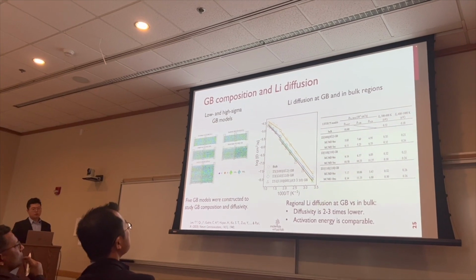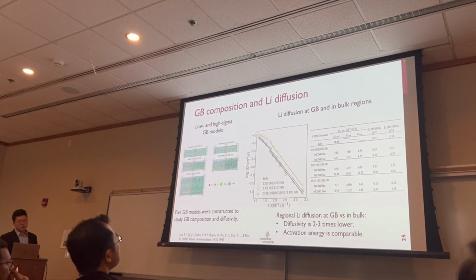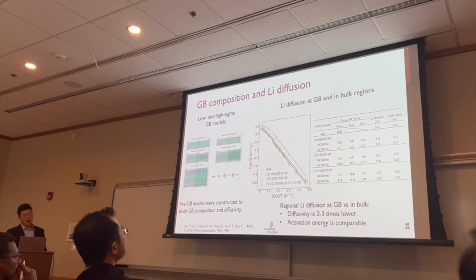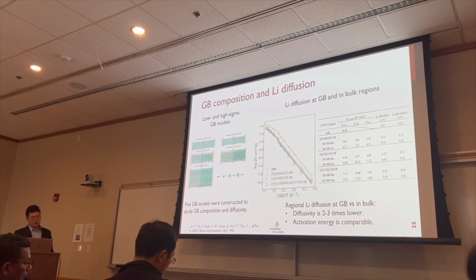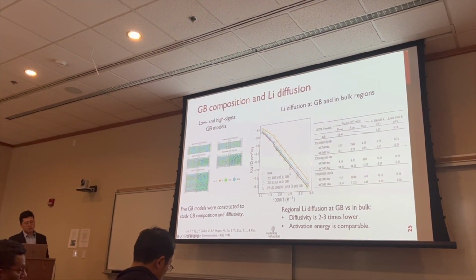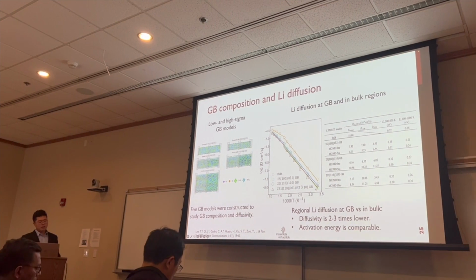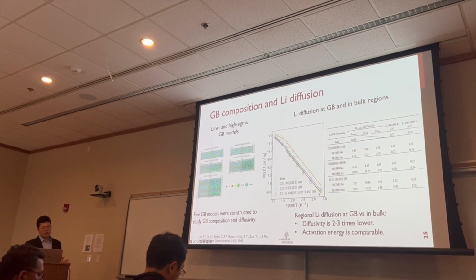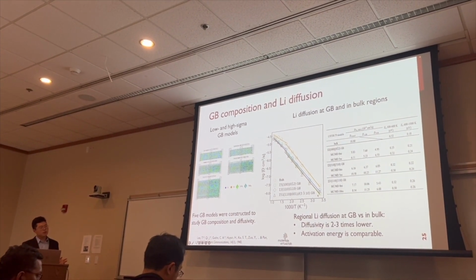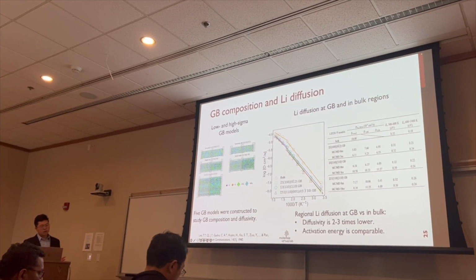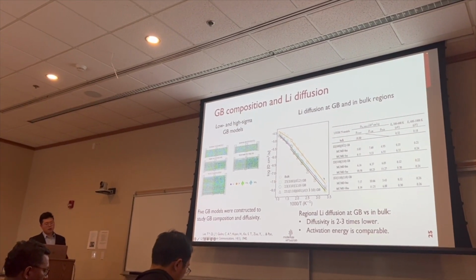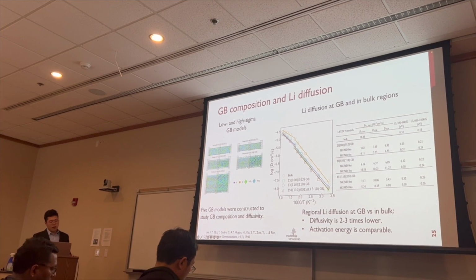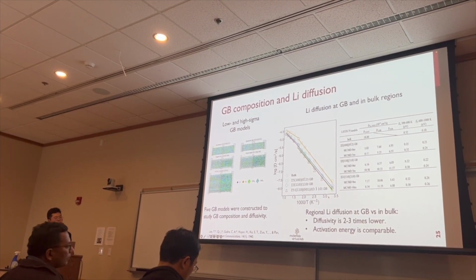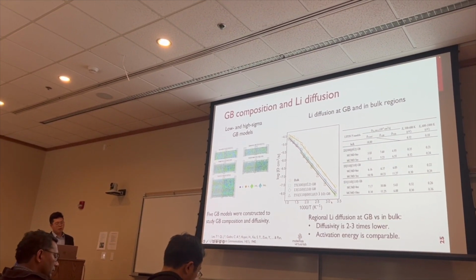And we also studied the Arrhenius plot with on-time MD simulation. And this time we see that for our system, by the analysis of lithium diffusion at grain boundary region, the diffusivity is only 2 to 3 times lower than the diffusivity in bulk, and the activation energy in grain boundary and in bulk are actually comparable.